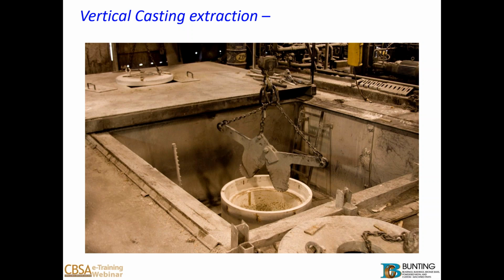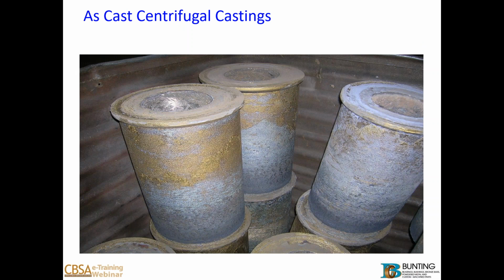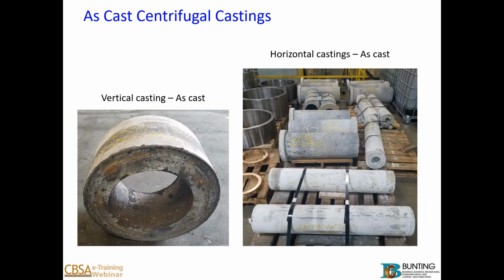So the next picture shows you how we extract the cast from the mold. The casting shrinks away from the die wall, allowing the casting to be removed safely. These are centrifugal castings, smaller ones, and you can see the impurities on the ID and the OD is pretty smooth, but we still machine the OD to prove the high integrity of the material. On the left, you can see a vertical casting, and this shows more how the impurities have all gone to the inside diameter, which we machine off. On the right-hand side, it shows the smaller OD, longer castings. The white residue on the outside of the casting is where the mold wash has actually baked on to the bronze material.